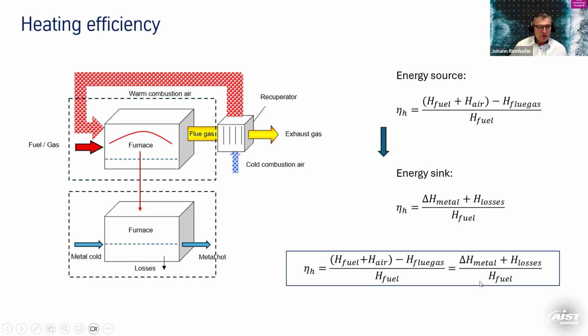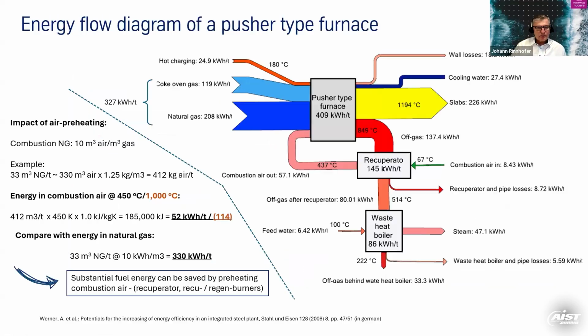So this is how you can calculate, and we don't do this in more detail here, the thermal efficiency of this furnace. For rolling mill furnaces, it is around 0.65, 0.7, 0.8 maximum, I would say, for a continuously operated furnace. So you always have some losses, and usually we will see that the flue gas loss is the highest loss.